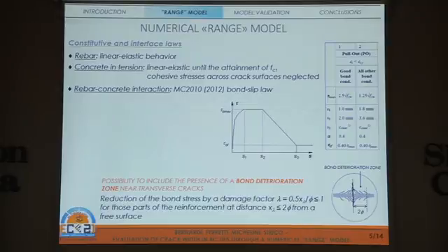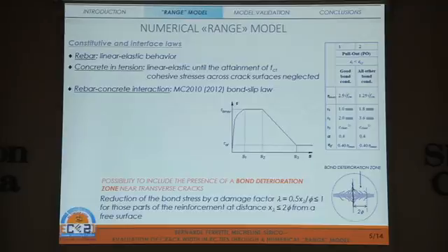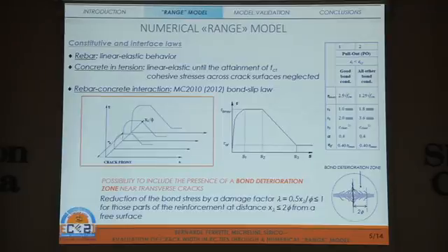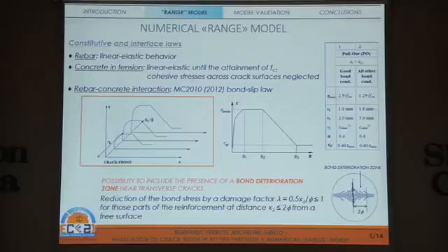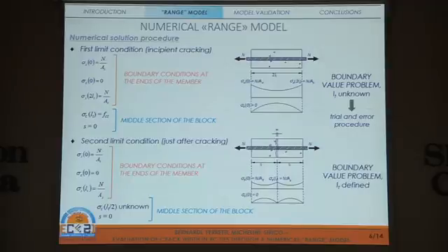The model also allows the possibility to include a bond deterioration zone near transverse cracks due to the splitting and crushing of concrete around the bar beside the crack. This effect is taken into account by reducing the maximum bond stress by a damage factor for those parts of the reinforcement at a distance lower than two times the rebar diameter from a crack. The differential equations are solved by means of a MATLAB routine based on the collocation method.